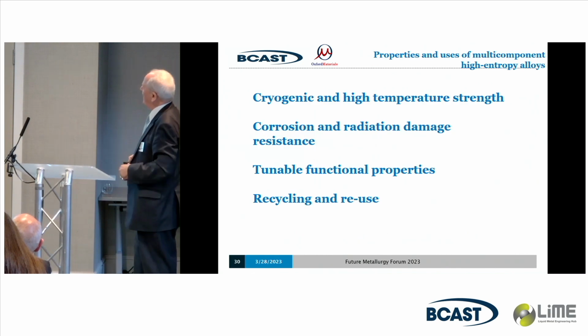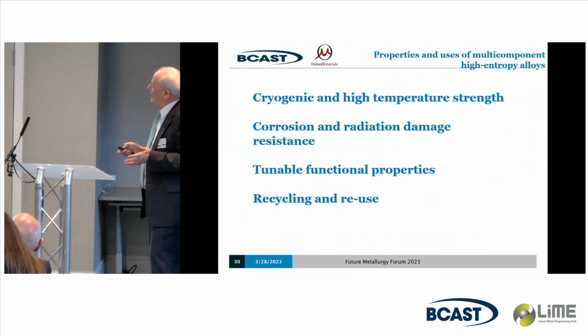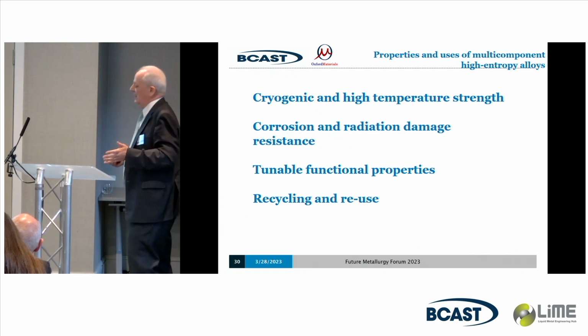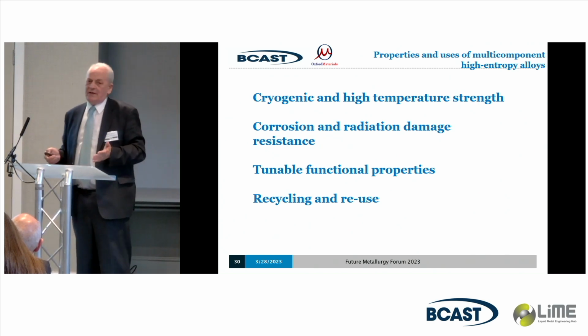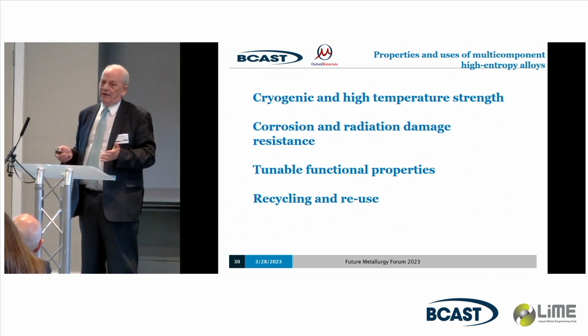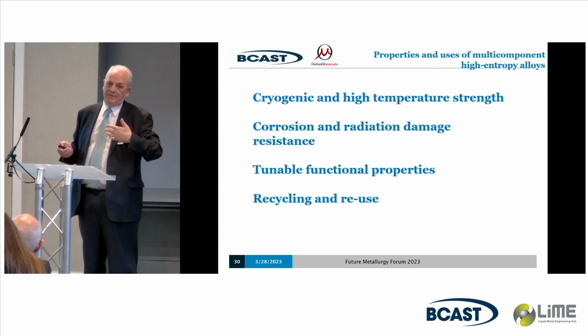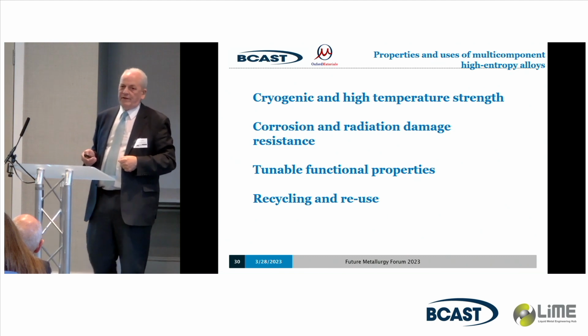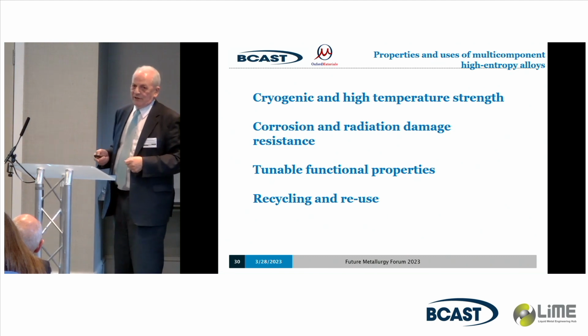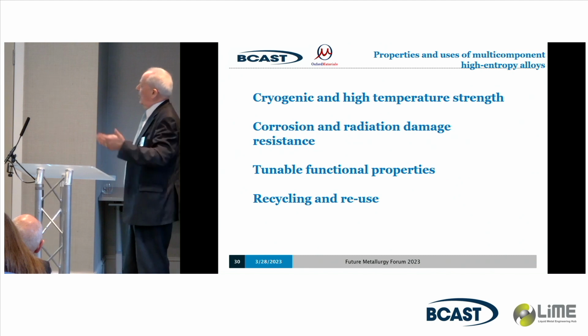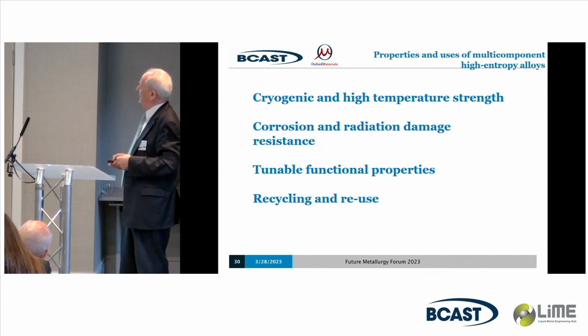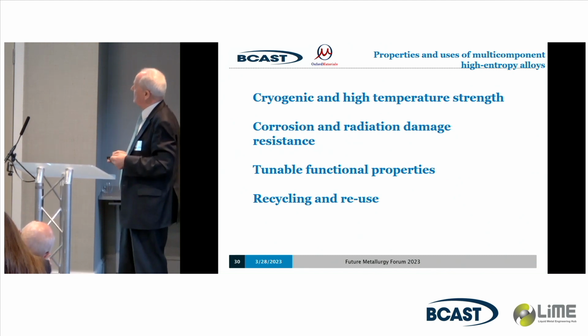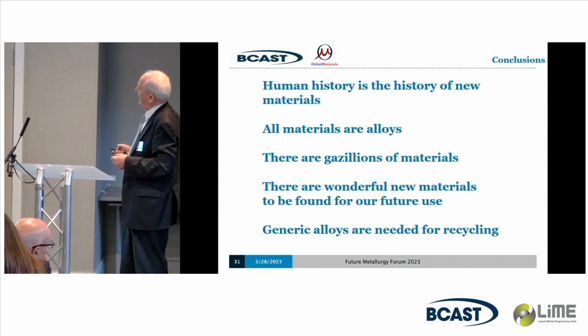I'm nearly finished. Just quickly then, the last slide, properties and uses of these materials. Well, the Cantor alloys have the best low temperature and room temperature properties in terms of fracture strength, fracture resistance and strength of pretty much any known material. You can argue it depends which you prefer best. They're particularly good on their ductility and fracture resistance and at very high strength.